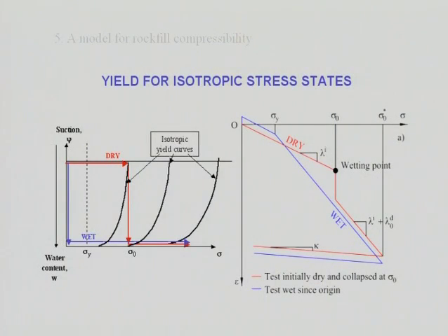It is much more useful to consider that from the perspective of hardening plasticity, and on the left you have the stress plane. But I have plotted here not a stress axis, but a measure of the energy of the water. It can be water content, it can be suction here, but it has no direct mechanical effect. However, if you start in a point such as this one, you load your sample, and what happens is that you drag your yield surface to a given point. And then, if at this given point you wet your sample, you drag again your yield surface to this second position here, etc.